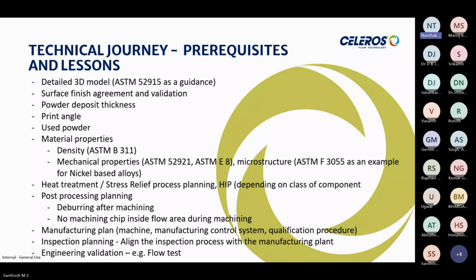The 52921 talks about the coordinates X, Y, Z, because the mechanical properties are based on direction. It changes slightly in the case of AM parts. So we need that standard to say how many coupons to take in the X direction, how many in the Y, and how many in the Z direction, and to find out which direction it is, you need the 52921. And then ASTM E8 is a normal standard that we use for tensile testing. So we use the ASTM E8.